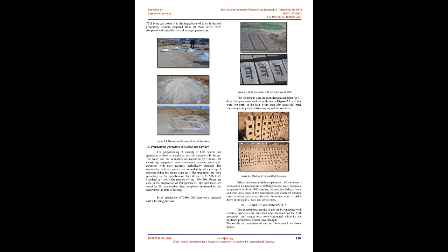For case C, i.e. waste bricks, specimen bricks of 230 mm x 100 mm x 70 mm were cast with varying proportions of constituent materials. The optimum mix proportion for preparing the base mix, BM, was decided as per the commercially available brick kiln manufactured bricks. Attempts were made to study and analyze the effect of partial replacement of brick clay with TPIS, in order to observe the effect of replacement along with maximum utilization of waste.